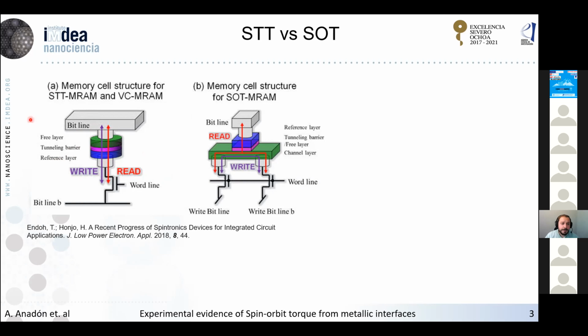This approach is very interesting, but it has some drawbacks that we have to take into consideration. The first one is that we need very high current densities to switch and to write basically the ones and zeros in the bit. And this sometimes may cause the tunneling barrier to be damaged, and this can destroy the bit of memory. Also, since writing and reading go through the same channel, there can be some false writing when you are trying to read. So to overcome both these issues, it has been proposed that a good way is to use